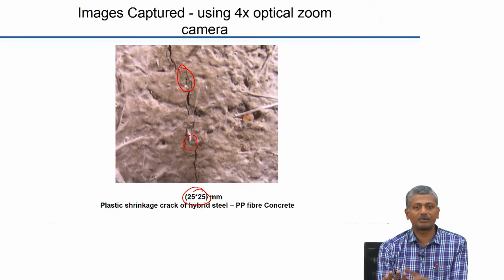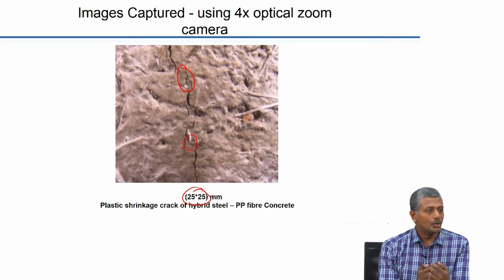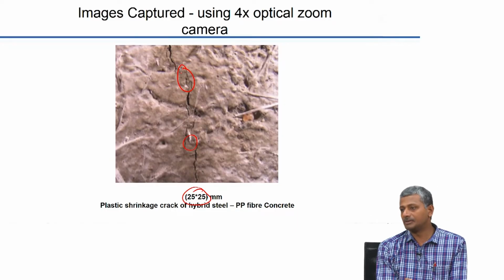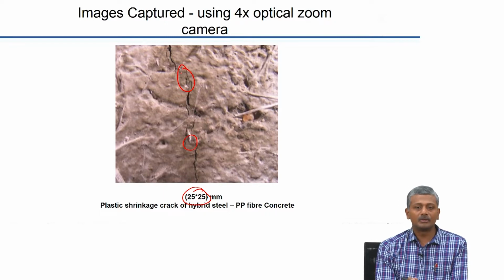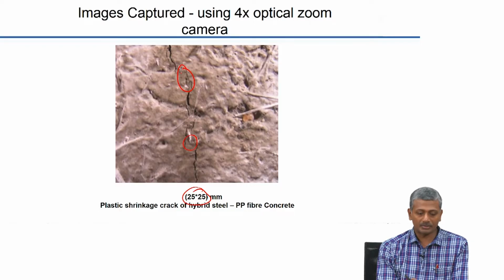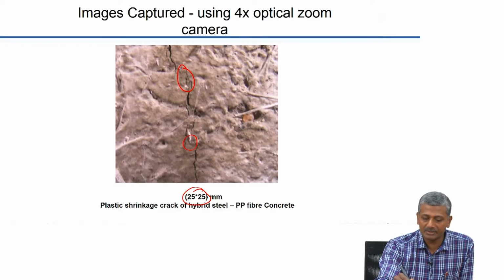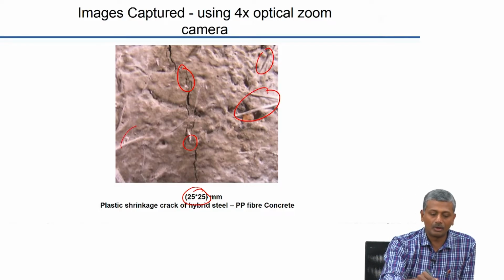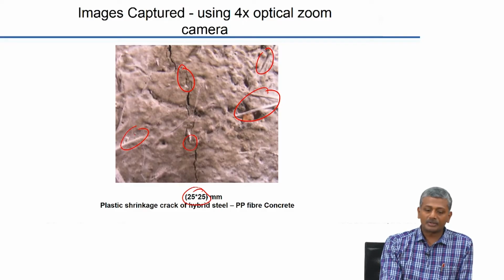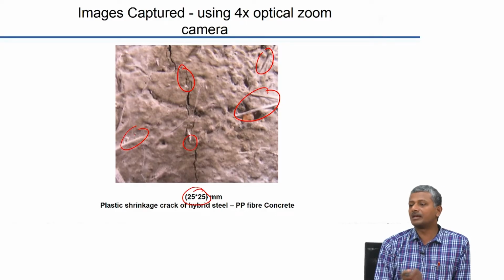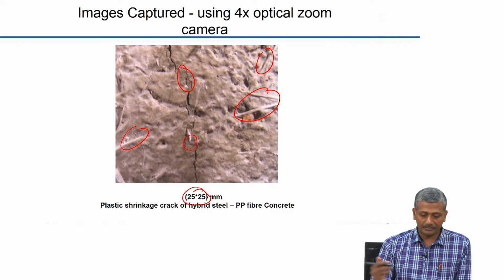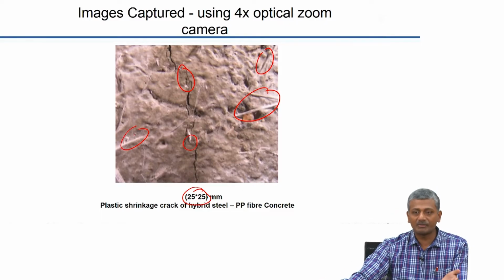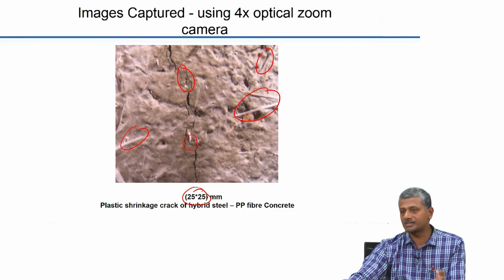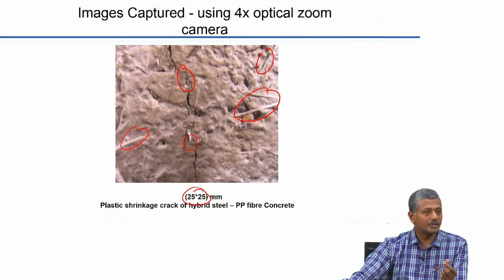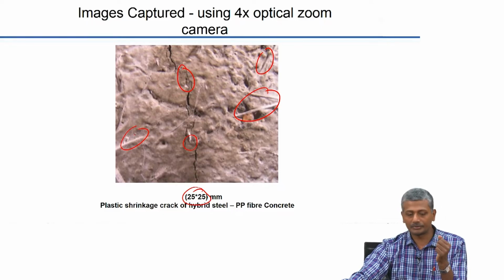Higher aspect ratio and lesser density implies you have a much larger number of fibers available, as a result of which there will be a much greater contribution to the reduction in cracking due to plastic shrinkage. So, here you can actually see even some fibers on the surface of the concrete, right. These fibers are so many in number that they are restricting cracking tremendously, and in fact, this effect was even better when we used polyester fibers, which were even thinner and shorter than the polypropylene fibers.